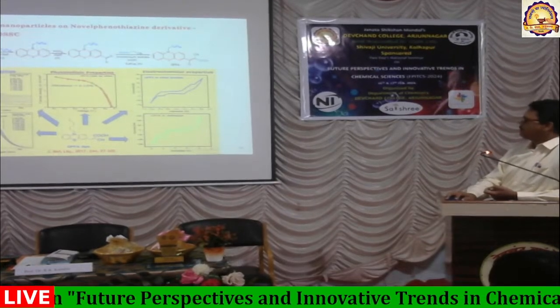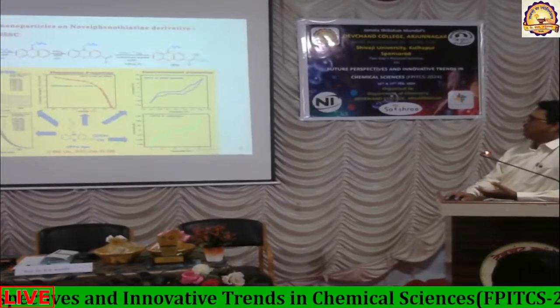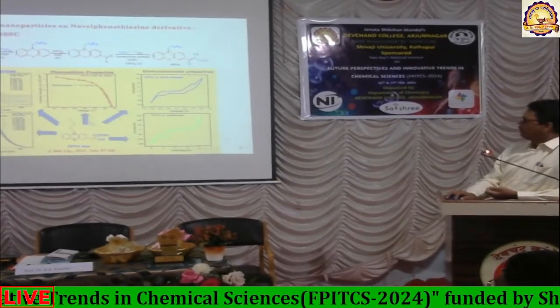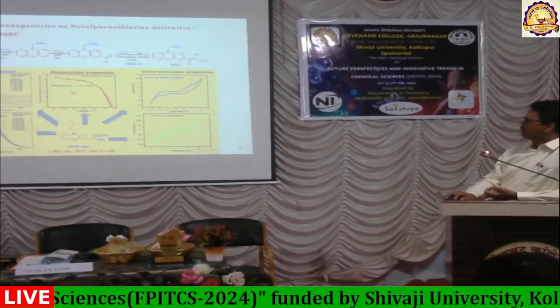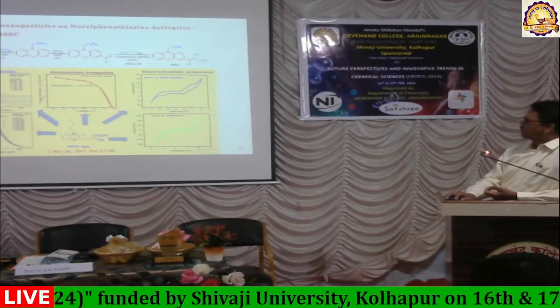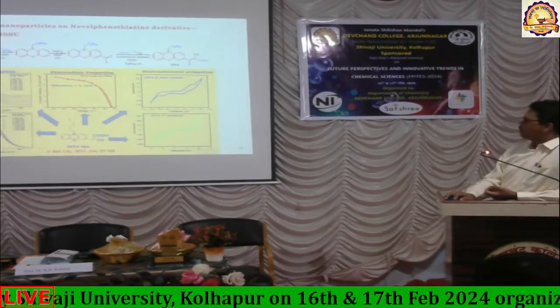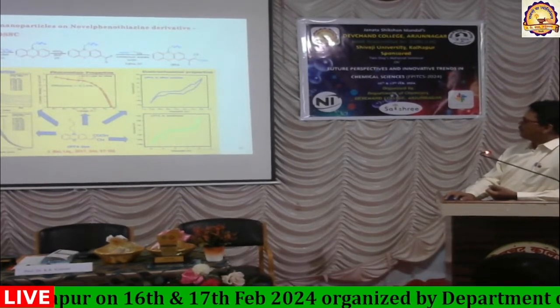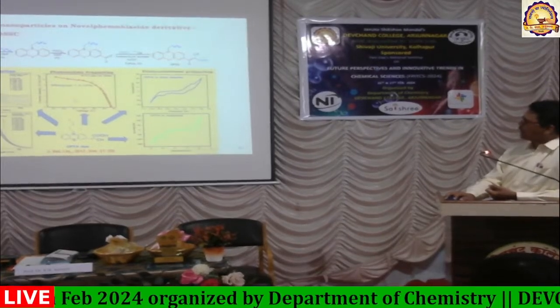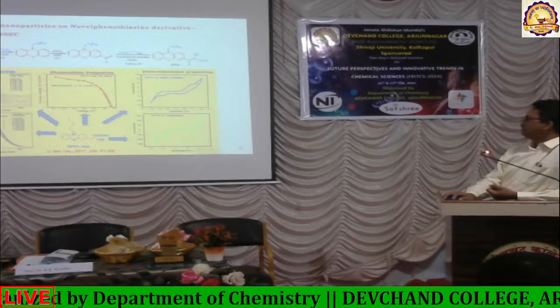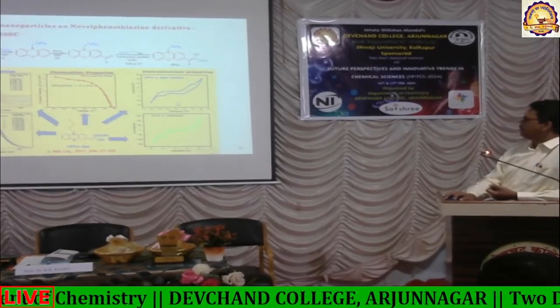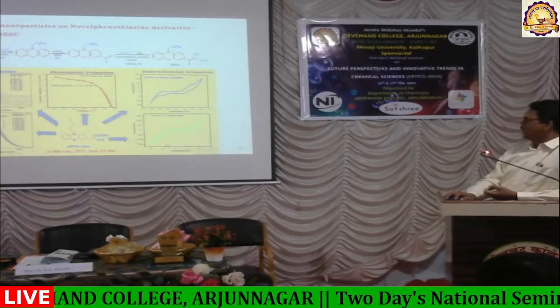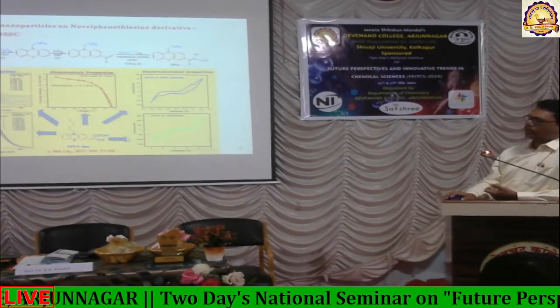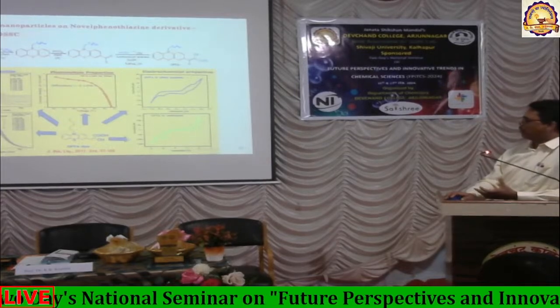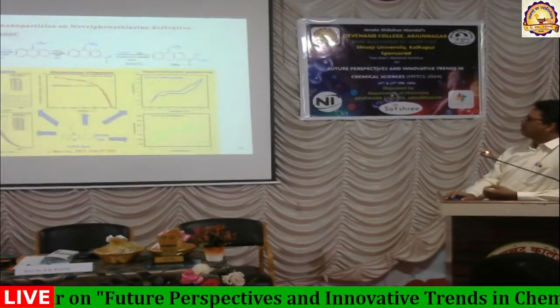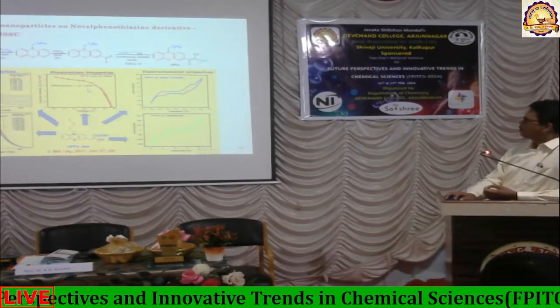This is required, where if it absorbs at this region, then only it will act as a very good dye. Okay. Then this is the kind of dye that we synthesized, and then these are the photovoltaic measurements, where we plotted current density versus voltage, and if this area, that is the fill factor, is more, the efficiency will be more. And we even did electrochemical properties like cyclic voltammetry, and we saw the oxidation and reduction potentials, and they are favorable. And with that, we calculated the energy difference between the highest occupied molecular orbital and lowest unoccupied molecular orbital. So the efficiency was found to be, in this case, 2.15%.